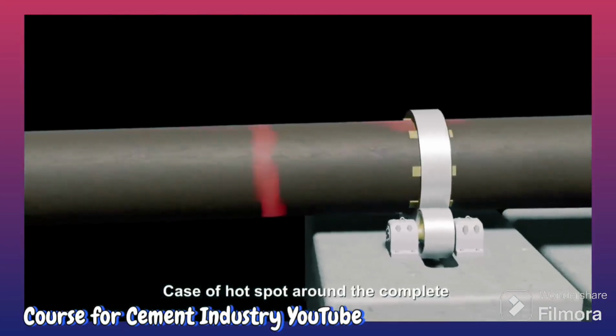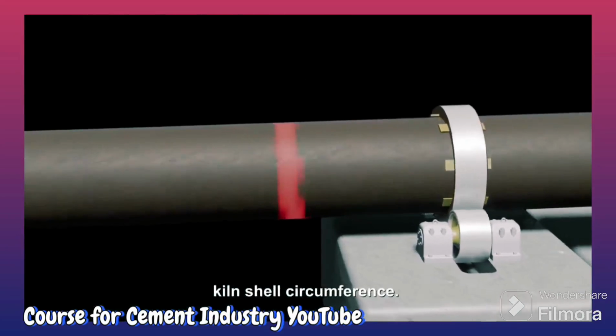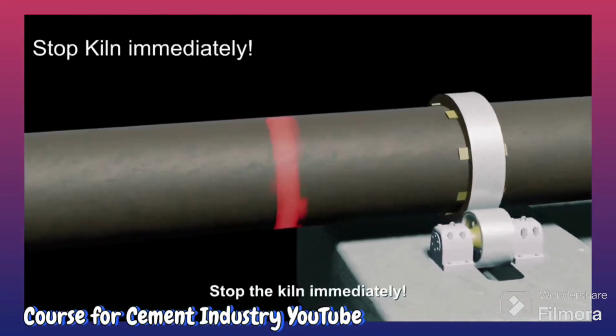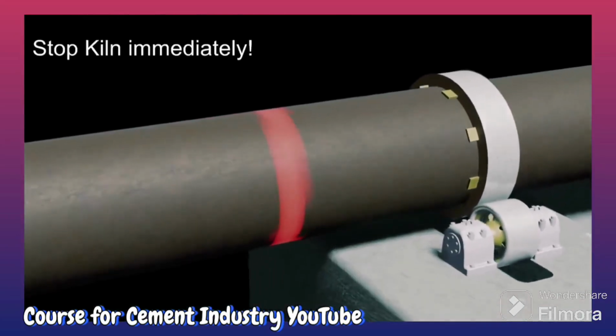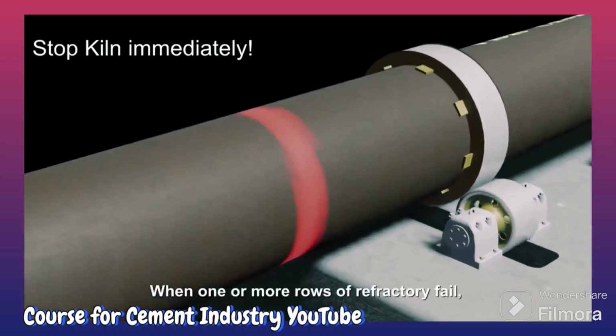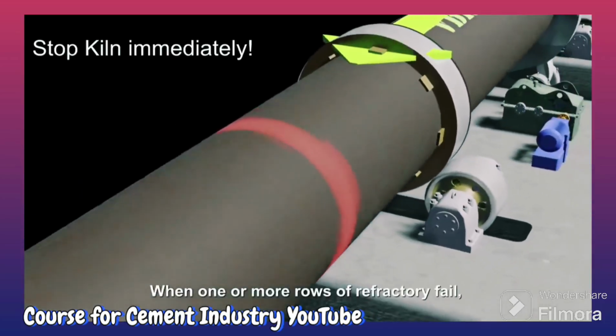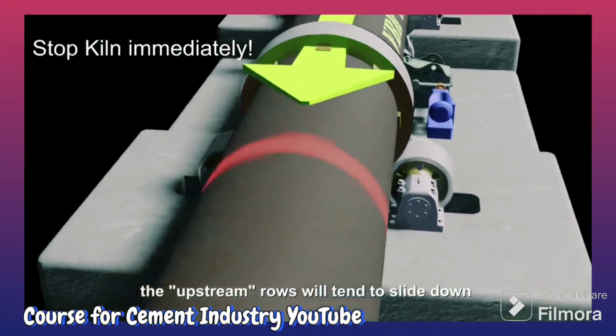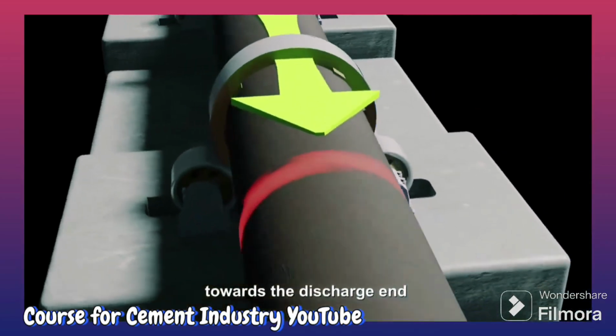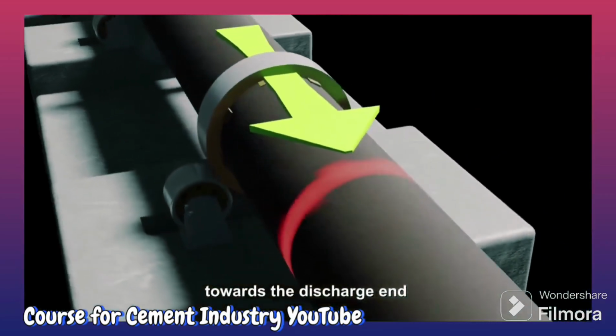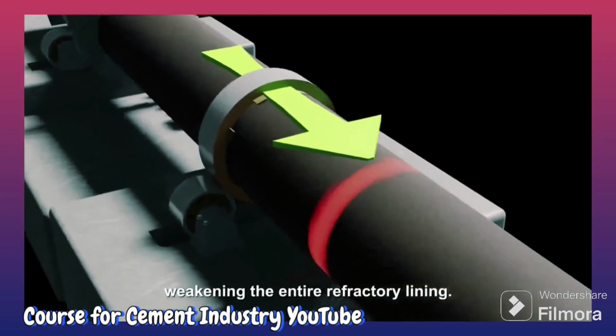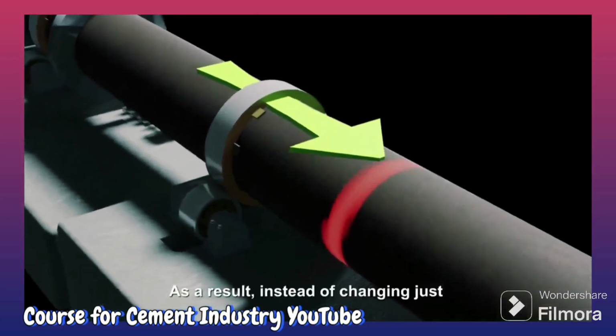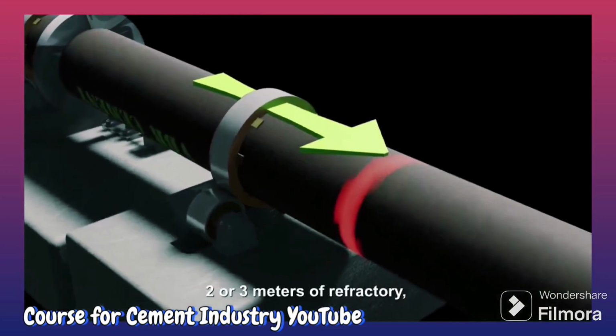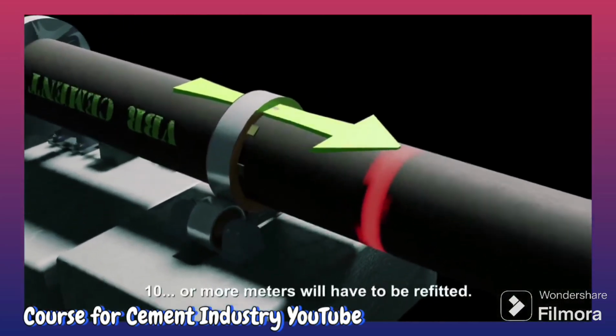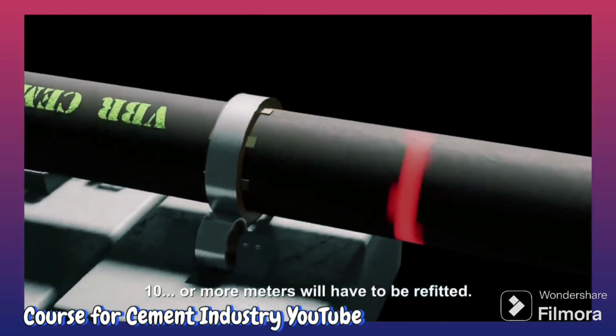Case of hot spot around the complete kiln shell circumference: stop the kiln immediately. When one or more rows of refractory fail, the upstream rows will tend to slide down towards the discharge end, weakening the entire refractory lining. As a result, instead of changing just 2 or 3 meters of refractory, 10 or more meters will have to be refitted.